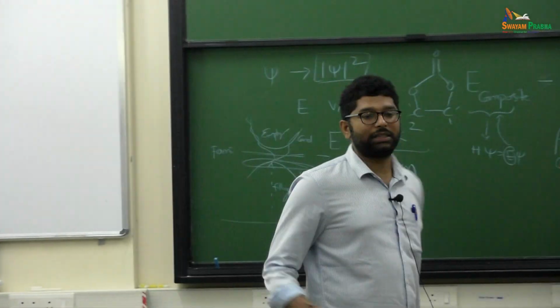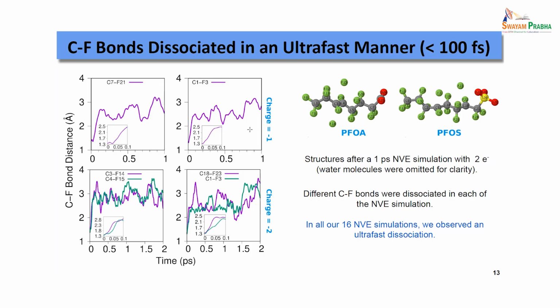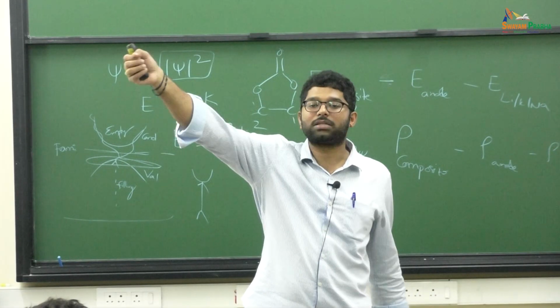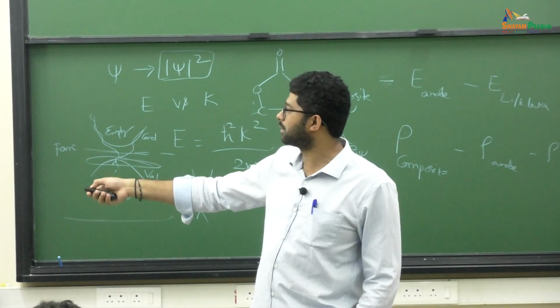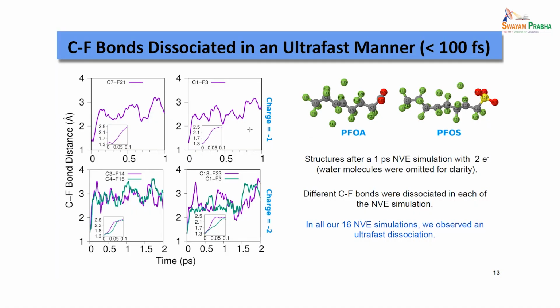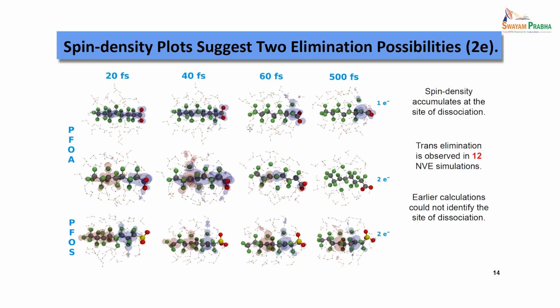So here 1.3 is for the CF bond distance, the equilibrium bond distance roughly. Okay, so this is the equilibrium bond distance, and as you can clearly see, these ones are going to 2.5. That suggests that the bond is dissociated. That's all this essentially suggests to you. So for -1 charge this is how it looks, and for -2 charge you are seeing clearly that the bonds are dissociated. And additionally we have also seen how this bond is actually dissociated.